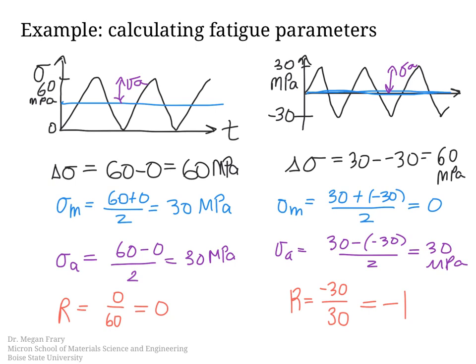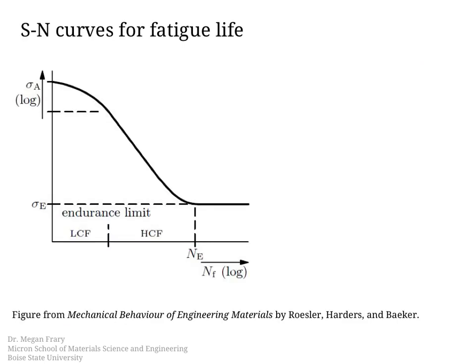So let's take a look now and see what the fatigue lifetime looks like as a function of the stress amplitude. So this is the kind of plot that would result if you measured the number of cycles to failure for a number of different experiments, using different stress amplitudes. So we're measuring the stress amplitude, we're recording the number of cycles to failure. Note that this is in a log-log plot.